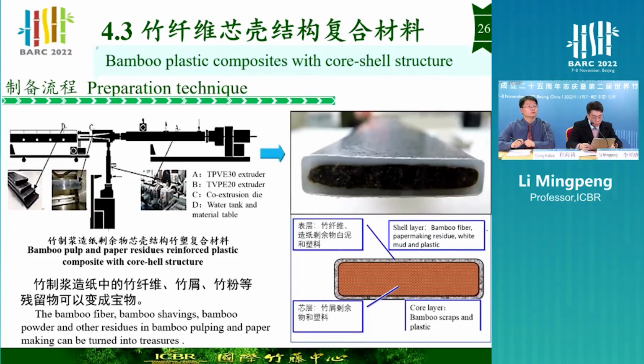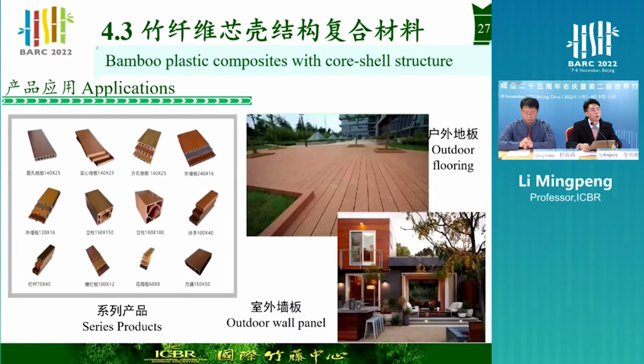For extrusion molding, bamboo fiber composite with core shell structure is produced by bamboo fiber, bamboo dust, bamboo powder, and resin from bamboo processing and paper making. The shell layer mainly includes bamboo fiber, paper pulp, residue, and plastic, while the core layer mainly includes bamboo residue and plastic, and the products are mainly applied to decking and outdoor flooring.